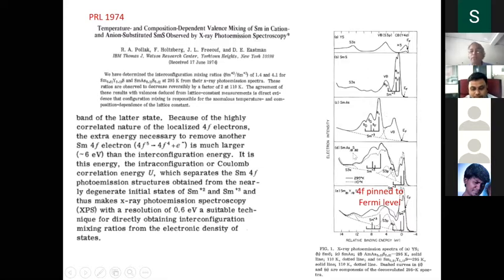When it comes to samarium, by the way, whatever is achieved at high pressure can be tuned by chemical doping. Same thing here: put in samarium sulfide, put in arsenic, and mix these two to make the compound. You find fingerprints of both samarium 2+ and samarium 3+, and this also behaves exactly like the high pressure phase of cerium or samarium hexaboride and things like that. They will be exactly like this.